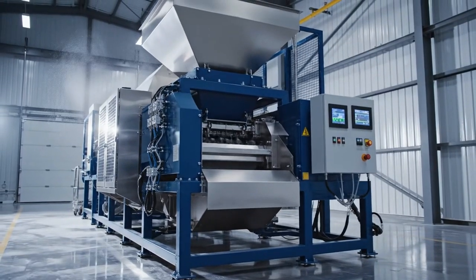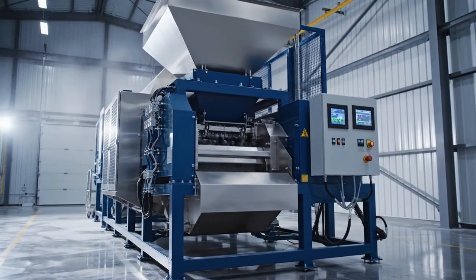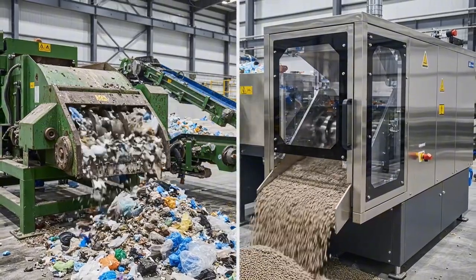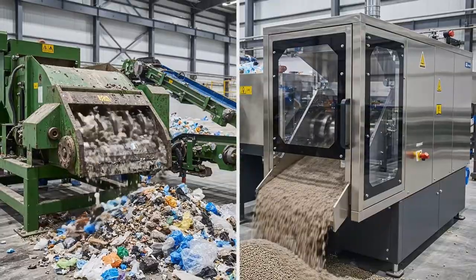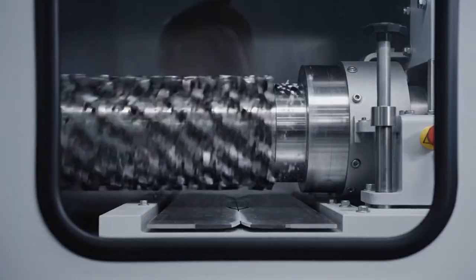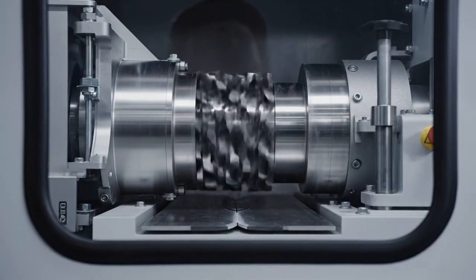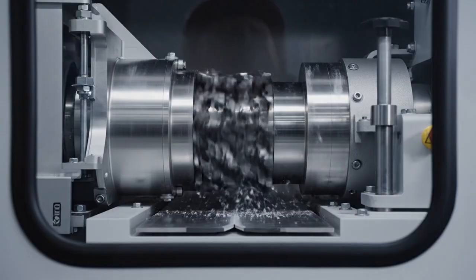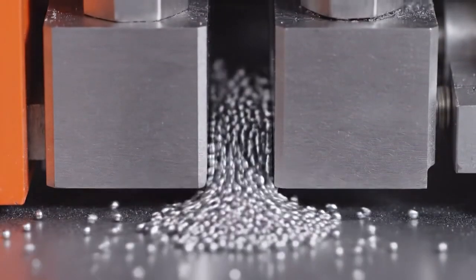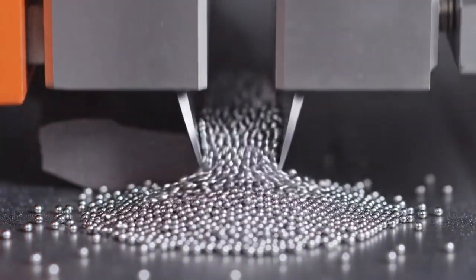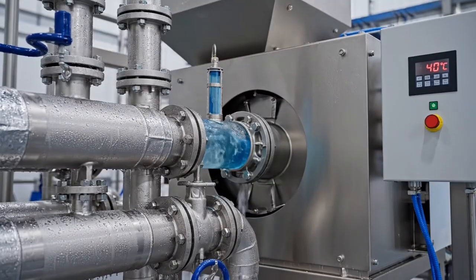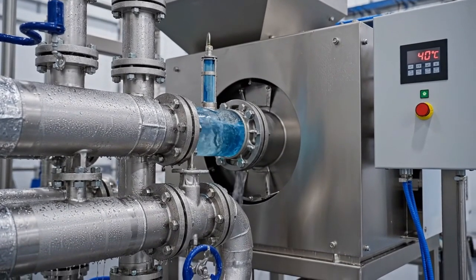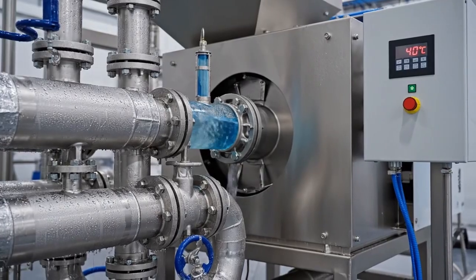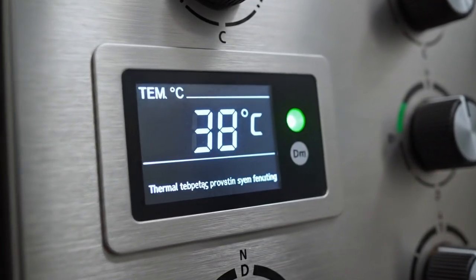The material now enters the domain of the granulator, a machine that represents the pinnacle of size reduction engineering. Unlike the aggressive brutality of the rough shredder, the granulator operates with calculated precision. Its rotor spins at 600 revolutions per minute, driving an array of cutting blades past a fixed bed knife with clearances held to within 50 micrometers. The cutting action is shearing rather than impact-based, producing particles with consistent size distribution. The granulator chamber is cooled with chilled water circulating through a jacketed housing, maintaining operating temperatures below 40 degrees Celsius to prevent thermal degradation of thermoplastic materials.